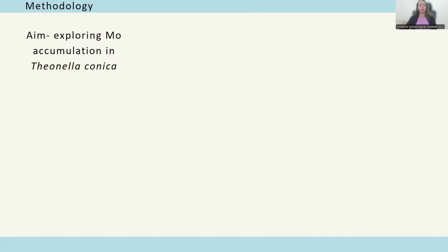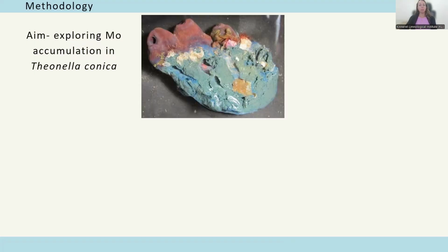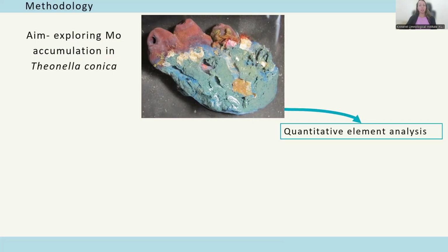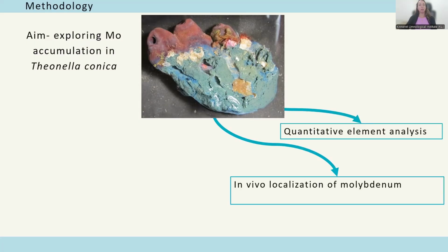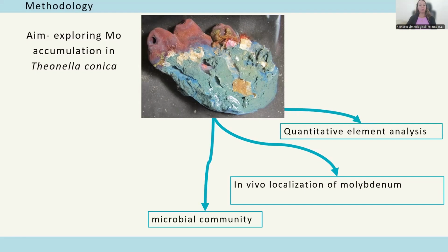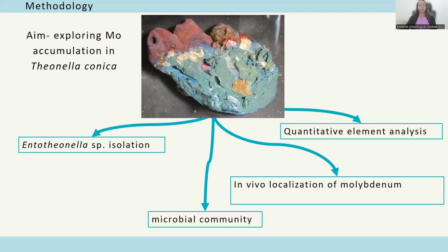This led us to design a workflow that moves from the whole sponge to specific fractions, cells, and intracellular structures. We started with sponge collection from the Red Sea and compared these samples with older samples from Zanzibar. For that, we used quantitative elemental analysis to measure the concentration of 22 elements, and we separated fresh sponge material into enriched fractions. We also used SEM-EDS to localize molybdenum-rich structures in the sponge body. And to identify crystalline phase, we used X-ray diffraction.